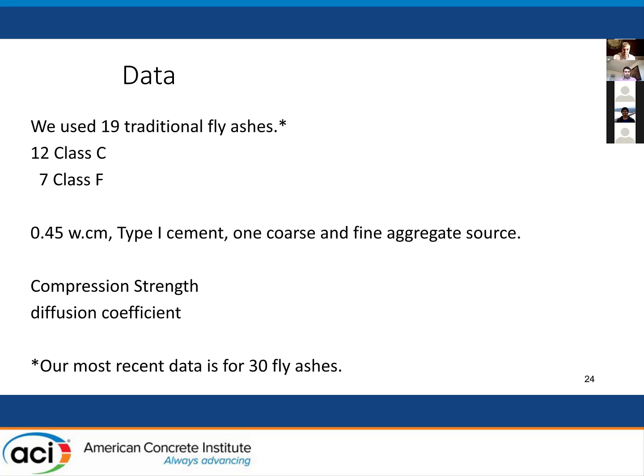We're going to use 19 different traditional fly ashes for the data I'm showing you today, but I'll give you some secrets here. We're up to 30 different traditional fly ashes, and we're up to 14 different reclaimed ashes. Things are looking really, really good with what I'm about to show you today. But we're going to test this in concrete. We're going to make a 0.45 water cement ratio, type 1 cement, 1 coarse aggregate, 1 fine aggregate. We're going to measure compression strength and diffusion coefficient for the data I'm going to show you today. But don't worry, we got a lot more data coming down the chute, right?